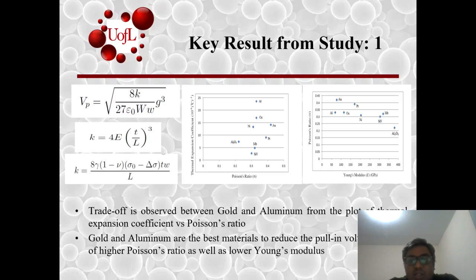And they found that there is a trade-off between the aluminum and the gold, because in case of the aluminum, the thermal expansion coefficient is the highest, but Poisson ratio is not the highest. But in case of the gold, the Poisson ratio is the highest, but the thermal expansion coefficient is not the highest. So from this plot, they have concluded that aluminum and gold can be the best candidate for the bridge material based on this graph.